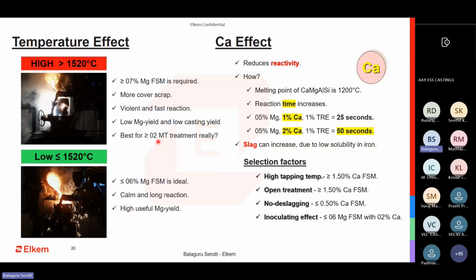It breaks the myth that if the treatment is more than 1 metric ton, I need to have high tapping temperature and higher magnesium. No, it is not the requirement. We need to understand that I just need to make sure that my temperature loss in the ladle is not high.